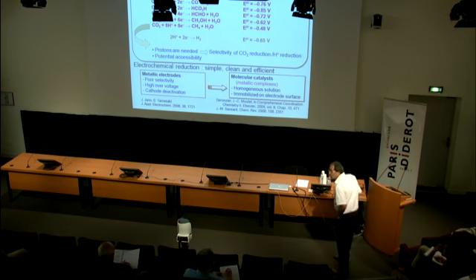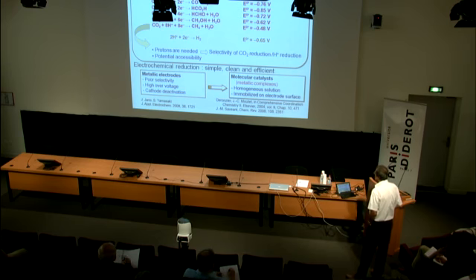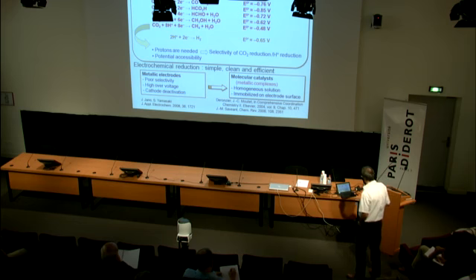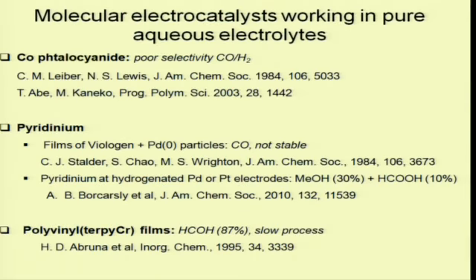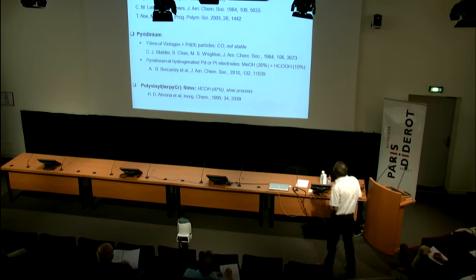It's called inner sphere reaction. So the process can occur in homogeneous solution or, more importantly, immobilized on the electrode surface. If you look at the literature about molecular electrocatalysis working in pure aqueous solution, there are not a lot. The first one was cobalt phthalocyanine, or a little bit previously, in fact. And there is a poor selectivity of production of CO versus the production of hydrogen. Another example are pyridinium derivatives.